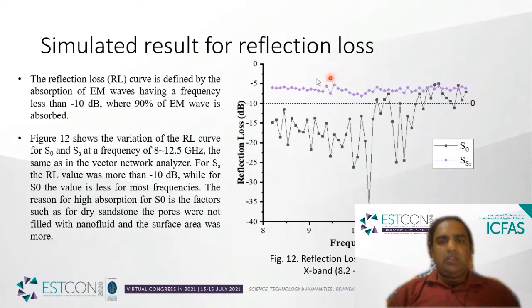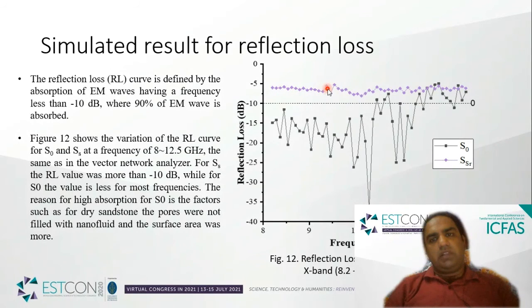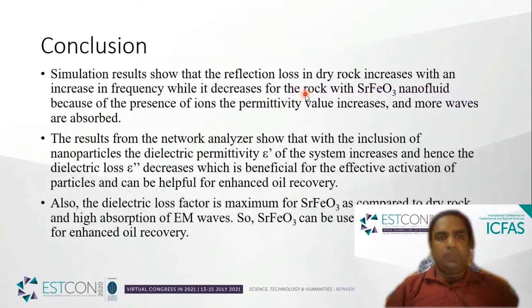But you can see that it shows a very consistent value for all the frequencies. The reflection loss is almost the same. But for the sandstone, at some frequencies the reflection loss is high, while at others the reflection loss is quite low, which tells us that we can use any type of frequency for enhanced oil recovery, for the strontium ferrite particles to get absorbed in the material.